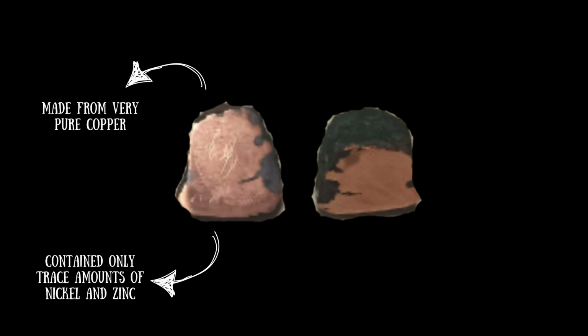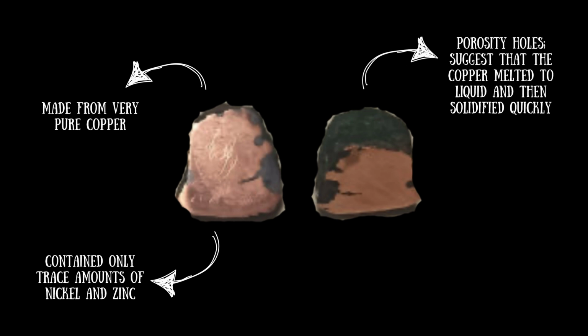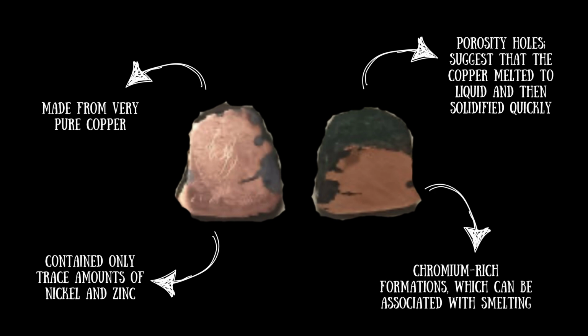Microstructural analysis revealed porosity holes, which suggests that the copper melted to liquid and then solidified quickly, and it also showed chromium-rich formations, which can be associated with the smelting of copper ores. The object also exhibited evidence of annealing after casting. For sure, the copper was exposed to high heat, but whether it was smelted or not, unfortunately, cannot be determined for sure with these characteristics.